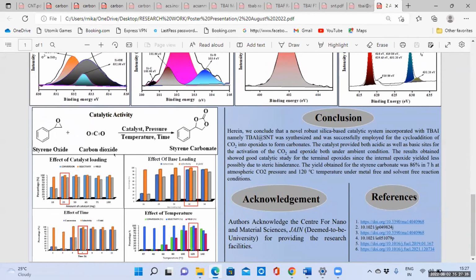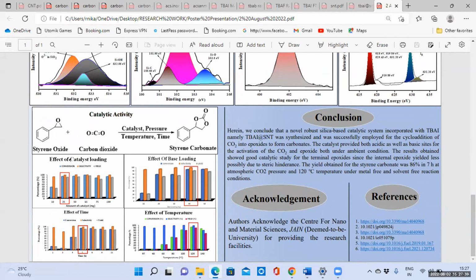The optimum result was obtained at 120 degrees temperature, 25 mg of grafted catalyst, 1 bar pressure, that is atmospheric pressure, and in 7 hours. The different effect of catalyst loading, base loading, time, and temperature was studied, in which in the effect of catalyst loading, 25 mg of catalyst gave best result. In case of base loading, 40 mg of base impregnation on SNT gave best results. In 7 hours gave optimum result, and 120 degree gave best reaction temperature.